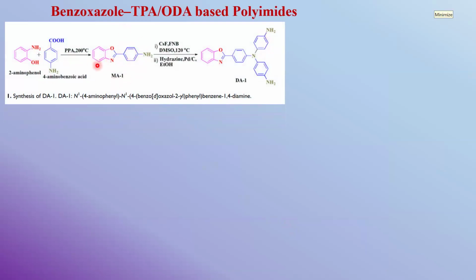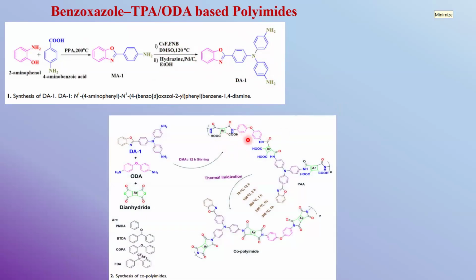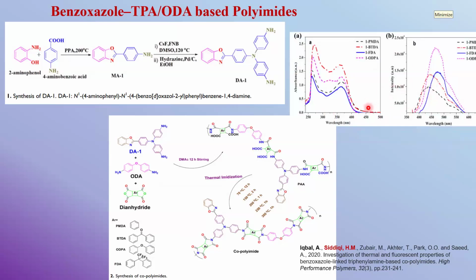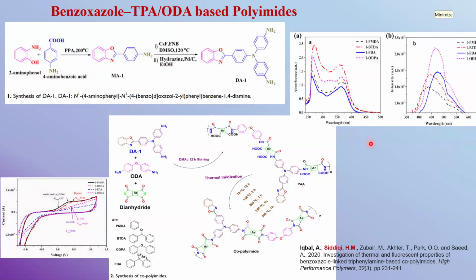benzoxazole formation. So benzoxazole was synthesized using 2-aminophenol in PPA at 200 degrees, and then we form its triphenylamine using cesium fluoride and fluoronitrobenzene, and then reducing the dinitro into the NH2 compound. So a diamine is again formed containing these aromatic groups. So these were also condensed with different dianhydrides, forming the copolymers with various dianhydrides. Their optical responses and their electrochemistry showed that they are good optoelectronic materials. So this was one of the works which was published in High Performance Polymers. Very briefly, I have talked about these optoelectronic materials which we have made using polyimides.